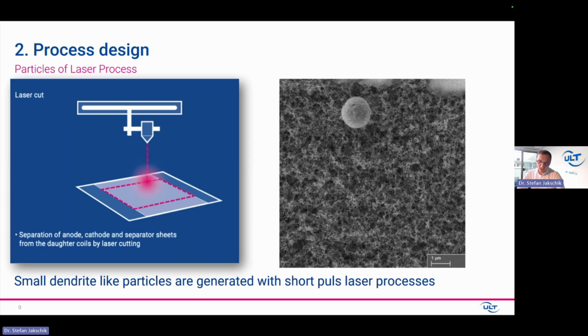So this laser process, which we just looked at, takes place like this. Very often you have scanner processes running over the electrode. And when we look at the particles, you see something like this, especially when you work with a short pulse laser. You have some balls, but mainly it's kind of woven, as you see here, very dendrite-like particles. For those of you who are aware of batteries, dendrites are very often lithium dendrites, but these are dendrite-looking particles from the laser slitting process, which could be on the electrode surface after this production process.